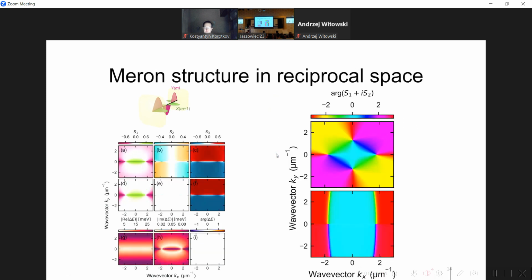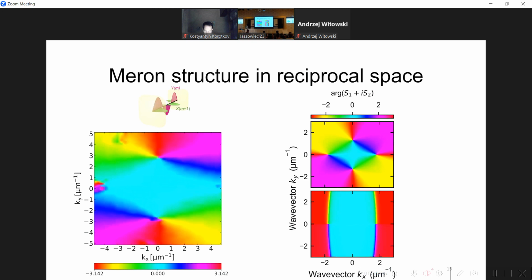Now, if we look further, for example at the n+1 regime, you can see that in such a case we can observe a Meron structure, which was depicted here as the argument of the complex Stokes polarization parameter. Here we have fully circularly polarized light, and here we have the Meron structure. But if you calculate the same using the simplified version, you cannot observe such a structure. And if you compare this data with experimental data, you see that only the upper branch, in which we include the rotation of bases during the calculation of polarization, is similar to the experimental data.